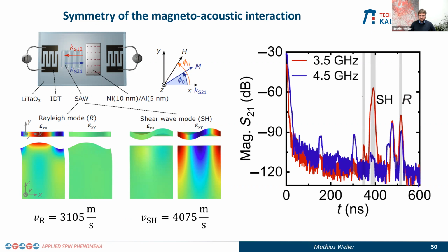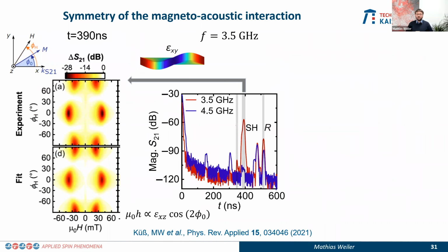Okay? And the nice thing is, this system basically supports both. So for instance, one can do time domain spectroscopy of the transmission of surface acoustic waves from left to right. Then one sees that after some time delay, about 400 nanoseconds or so, you see the arrival of the shear wave, and then it takes a bit longer, and the Rayleigh wave arrives because it's slower. So you can pick a frequency, for instance 3.5 gigahertz. You get a very nice shear horizontal wave, but you also get a Rayleigh wave at the same frequency. Okay? And now we can fix this frequency to 3.5 gigahertz.